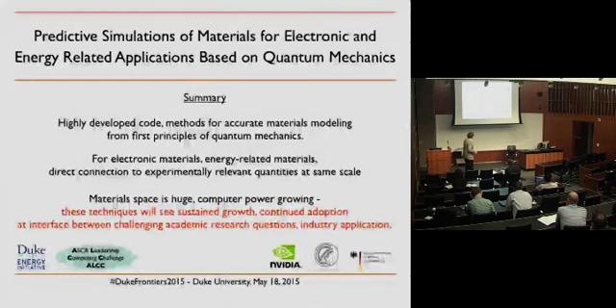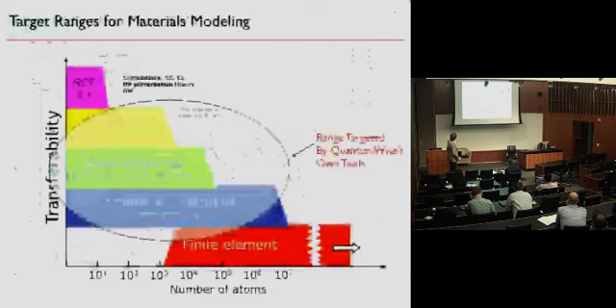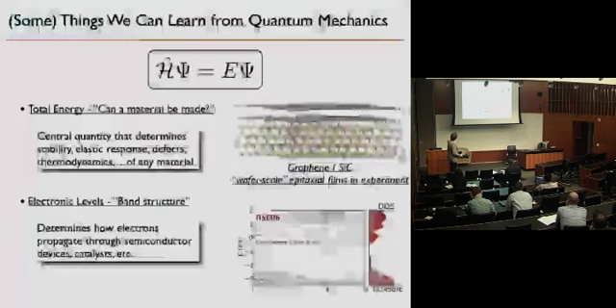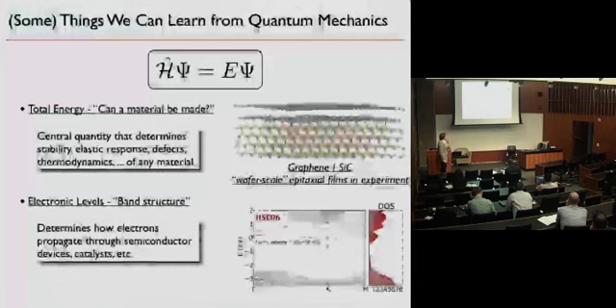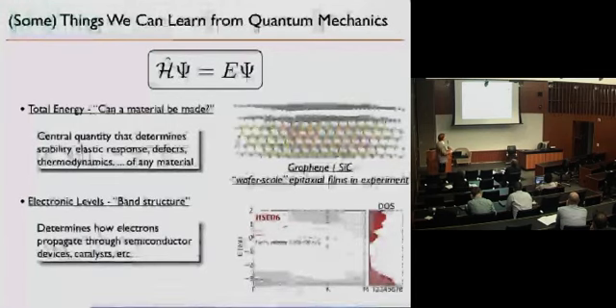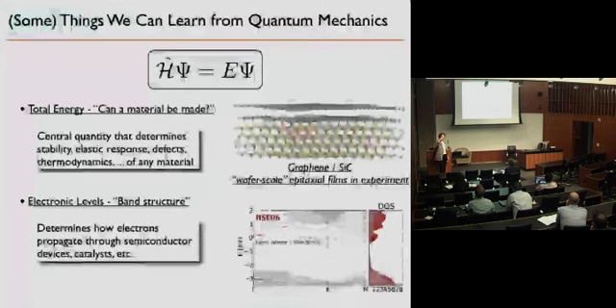Right, so it was actually in that case a relatively similar case. So this is this material here that I didn't talk about much due to lack of time. This is a material that's also been made for 10-15 years now. It was made earlier, but at that time people didn't realize they were making graphene. The nice thing about graphene on silicon carbide is that you can make graphene directly on an insulating, so semiconducting material without having to transfer it there.